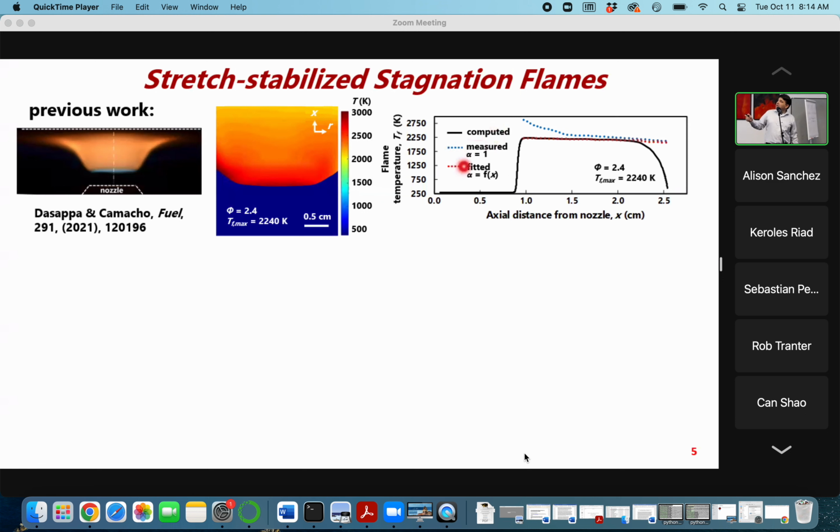an assumption commonly employed in this black body based formulation is that you can assume this emissivity coefficient of 1. And when we apply that assumption, we get a very much higher temperature than is probably there, approaching 3000 Kelvin. So our measurement is still not totally defined, but what we did was compare this to our gas phase computation.